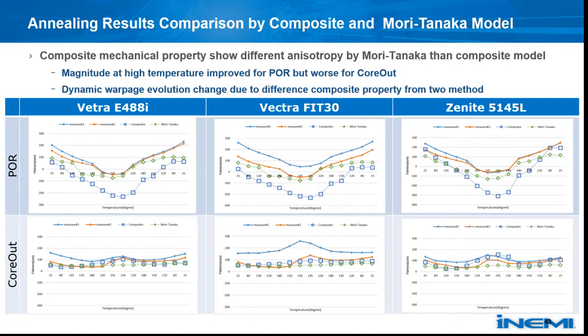So here is the dynamic warpage comparison. The hollow green diamond presents the result from input by Mori-Tanaka model, and we can see the results from the Mori-Tanaka model are relatively close to the measurement result compared to the result by composite model for the POR design. And for the core design, it is a little bit worse. The dynamic warpage evolution changes are due to the overall composite property being different from the two input methods. Next page.